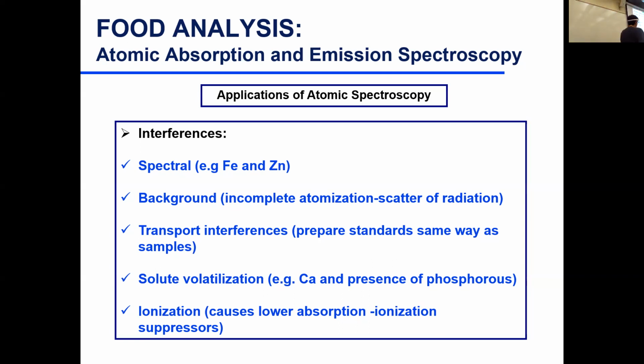To avoid that, you add lanthanum chloride. Lanthanum would replace the calcium and react with phosphorus. Therefore, calcium will be released and will be solubilized and aspirated into the flame. So that's why for calcium determination, you will be adding lanthanum chloride, but for iron, that doesn't happen, there's no problem, so you don't add lanthanum chloride.